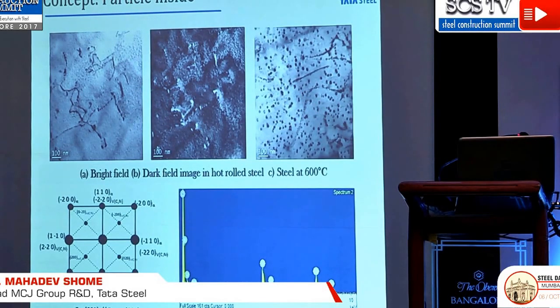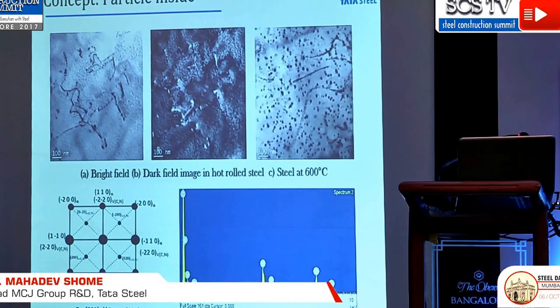The intent was that as the temperature rises because of the fire to 600 degrees centigrade, these precipitates would evolve out of the matrix and retard dislocation movement and provide the necessary fire resistance properties. Okay, so with that sort of alloy design and engineering, we arrived at this sort of precipitates at high temperature, and confirmed by these SAD patterns and X-ray diffractions to confirm the sort of precipitates we were looking for.